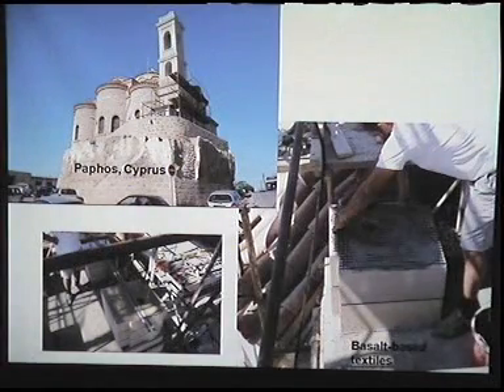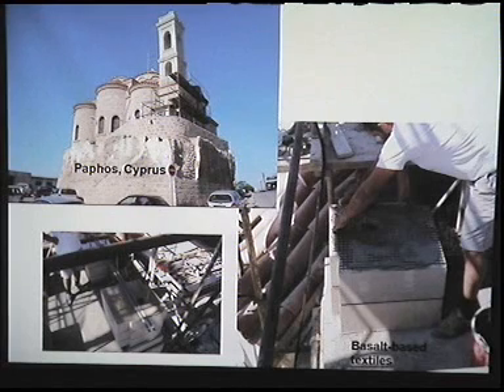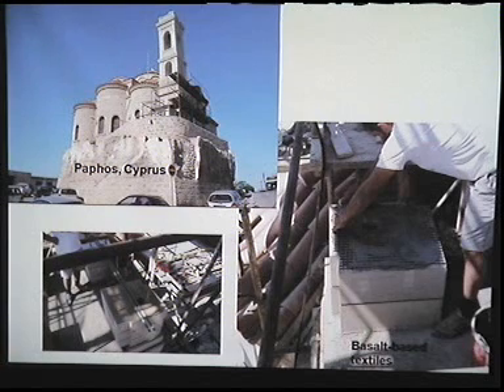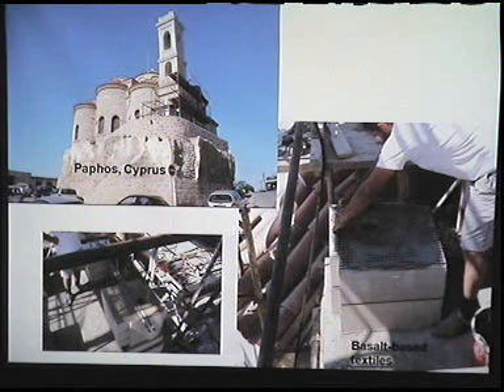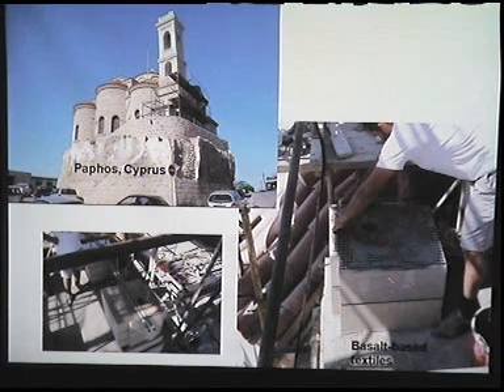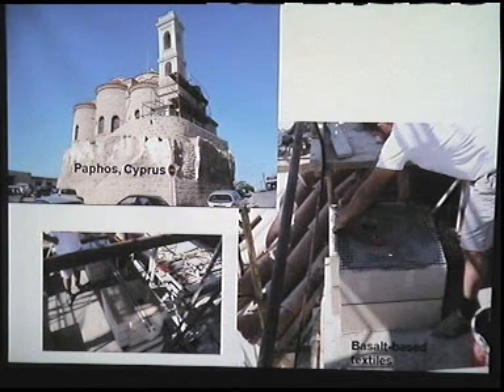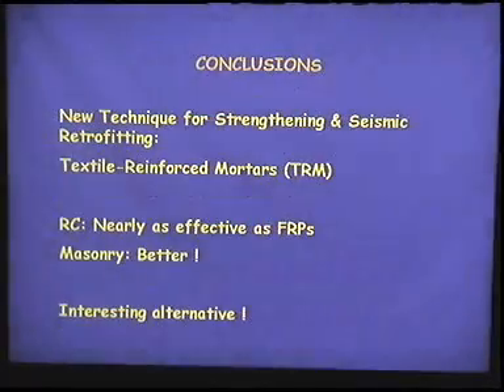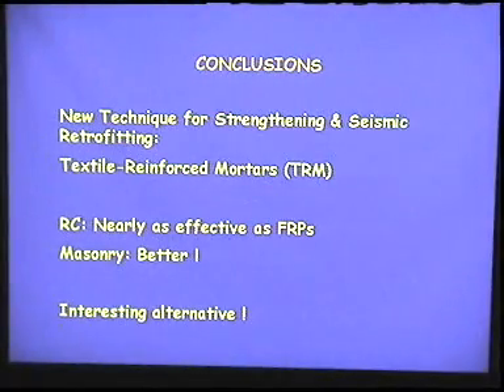Another application from a historical church in Cyprus, in the city of Paphos, where this bell tower had to be rebuilt, to be reconstructed. It was done with bricks strengthened at the interface with a mortar, with basalt-based textiles bonded with an inorganic mortar compatible with the bricks. My conclusions are that we have at our disposal a new technique for strengthening and seismic retrofitting